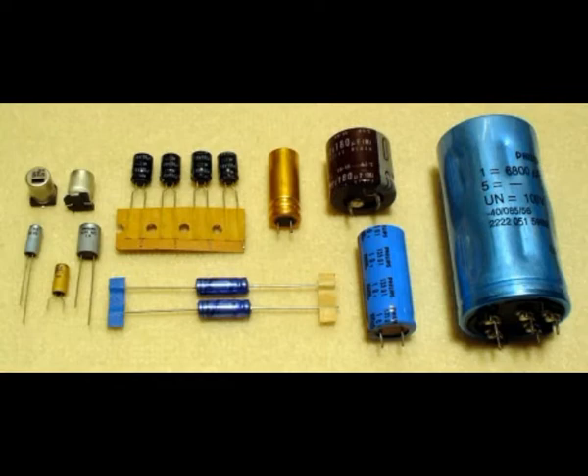If the outside circuit is high ohmic, the capacitor fails and the vent opens due to high gas pressure. If the outside circuit is low ohmic, an internal short circuit is more probable. In every case, a reverse voltage lower than -1.5 volts at room temperature may cause the component to catastrophically fail due to a dielectric breakdown or overpressure, which causes the capacitor to burst, often in a spectacularly dramatic fashion. Modern electrolytic capacitors have a safety vent that is typically either a scored section of the case or a specially designed end seal to vent the hot gas, liquid, but ruptures can still be dramatic.